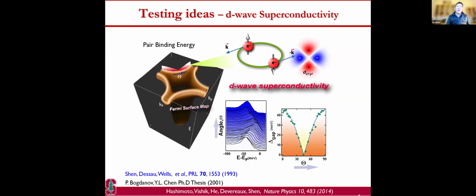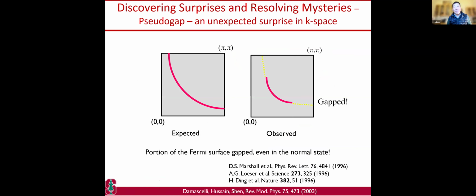Among the Cuprate problems, there are a few things on which we all agree today. One of them is d-wave superconductivity. Here is the map of the d-wave gap along the underlying Fermi surface; the dots are the data, and the solid line is the d-wave gap form. Then there's another issue, the so-called pseudogap. This has been around for almost 3 decades and is one of the persistent challenges in Cuprate research.